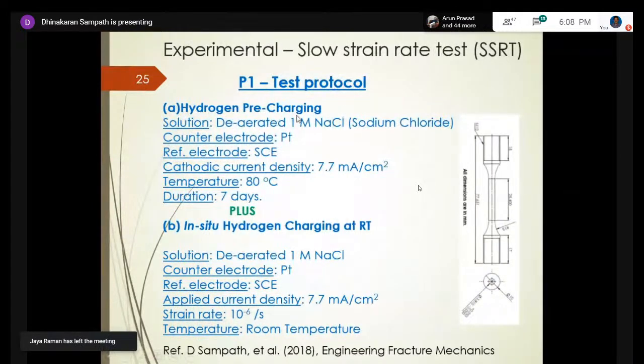For the test protocol, hydrogen pre-charging just used a three electrode system to have an electrochemical reaction generating hydrogen on the surface. We apply a cathodic current density of 7.7 milliamp per centimeter square. It's a constant current density based on the surface area exposed, at a temperature of 80 degrees for 7 days. Since nickel alloy is FCC, face-centered cubic material, it will have low diffusivity. Even after 7 days, with this diameter of 3.81 millimeters, it will reach only an annular radius of about 200 micron roughly. So it takes longer.